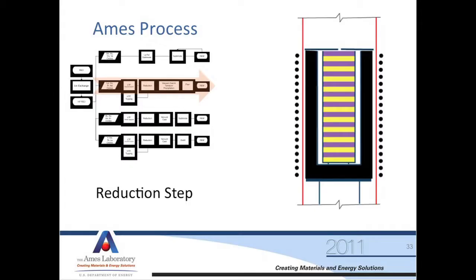and we do the reduction. Well, if we imagine that these purple lines are layers of neodymium fluoride and the yellow lines are layers of calcium metal, this is how we'd pack the reduction. It's almost like packing sand in some cases, and you're doing this in a 10-inch tall crucible. So it's not very fun for our technicians to do it, but they do a good job of it.